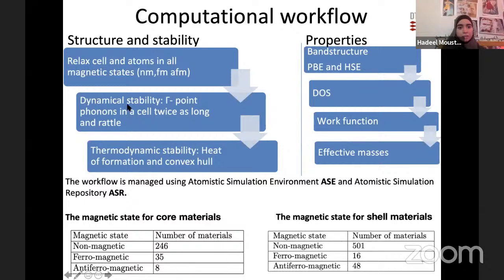We looked at the dynamical stability and the thermodynamical stability. For the properties, we calculate the band structure using PBE and HSE. We calculate the density of states, the work function, and the effective masses. The workflow is managed using the Atomic Simulation Environment and the Atomic Simulation Repository.